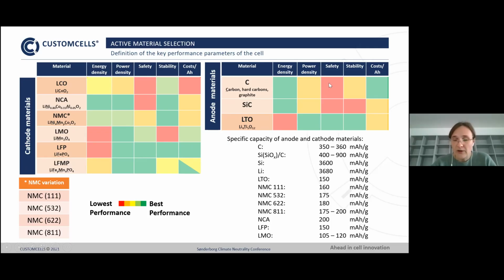On the anode, on the other hand, usually carbon is used, either graphite, hard carbon, or carbon. This material has a high energy density. You can see that here in comparison to all the cathode materials, it already has a very high specific capacity. However, the lithium, when it is intercalated into the carbon, is very close to a metallic lithium and therefore very reactive. That's why the safety and stability of this material can be an issue.